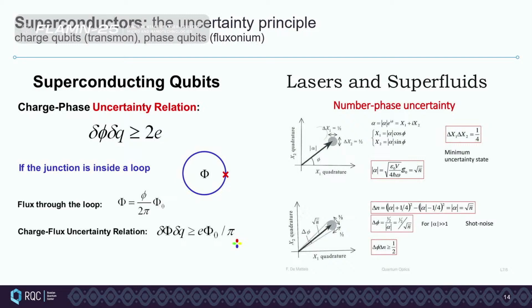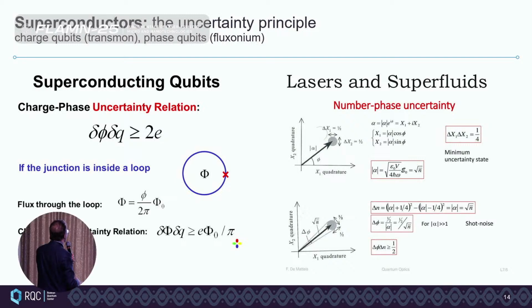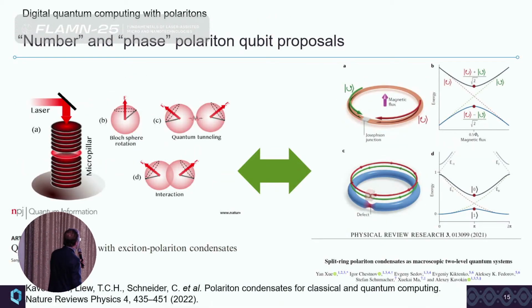So in superconducting qubits, both ways have been exploited, and the most popular is the charge qubit or transmon, but also phase qubits have been implemented, fluxonium, and in some characteristics, fidelity is better than in charge qubits. In polaritons, the proposal for the number qubit was formulated and studied in Singapore, in particular by Tim Liew and Sanjib Ghosh, but it was not yet experimentally implemented because a single polariton has a very short lifetime. If you make a qubit based on a condensate and condensate plus one excitation, then the lifetime of this qubit would be limited by the lifetime of this excitation, which is 10 picoseconds. And then you cannot do much with that.